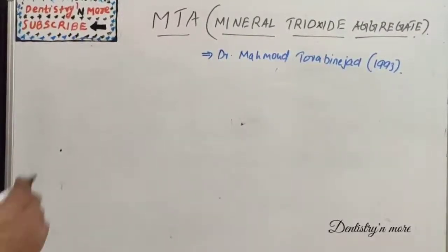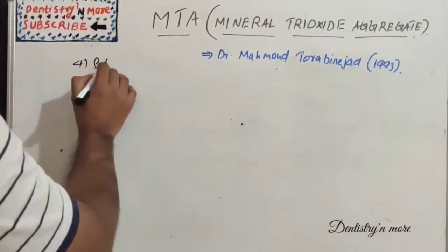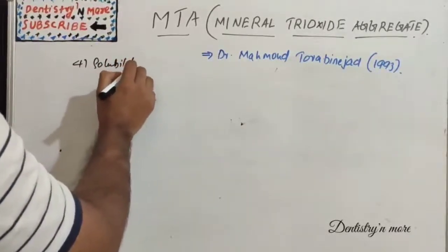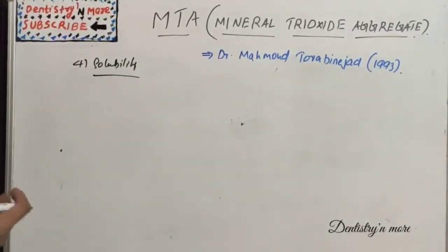The next property, the fourth property, is solubility. MTA shows basically no sign of solubility, and the solubility might increase if we add more water during the mixing. The set MTA, when exposed to water, releases calcium hydroxide, which might be responsible for its cementogenesis property. So that is solubility. The next thing is marginal adaptation.